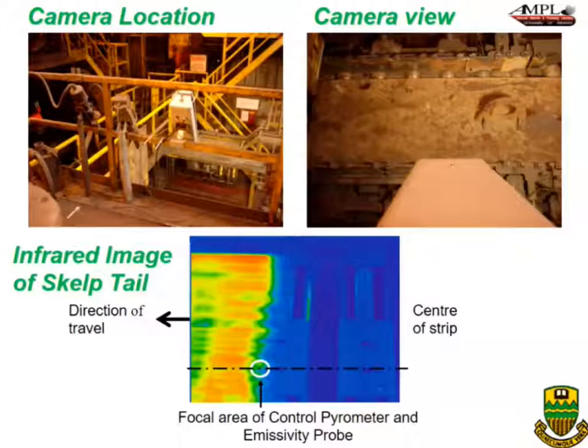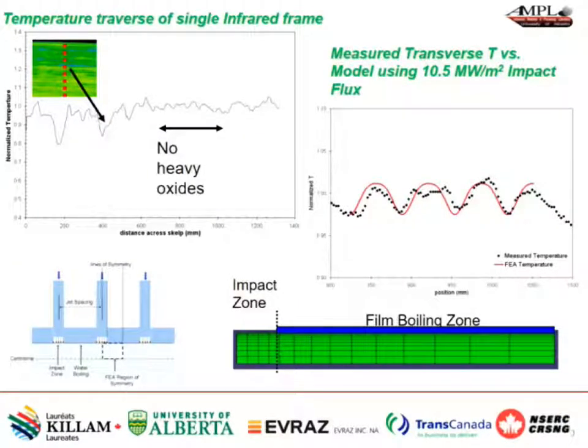And this is looking down on this surface, and this is an image of the trailing edge of a strip as it's going by. This is the center of the strip, and so you get an image of the whole strip, but also you can focus on any particular region and get the emissivity and the temperature at that particular region. So here is a sample of the temperature. It's normalized for obvious reasons, but this is the fluctuations of the temperature across the surface of the skelp. This is this particular line here, for example, this point being that one here. And if you look at this in more detail, what you see is these fluctuations in temperature as a function of position.